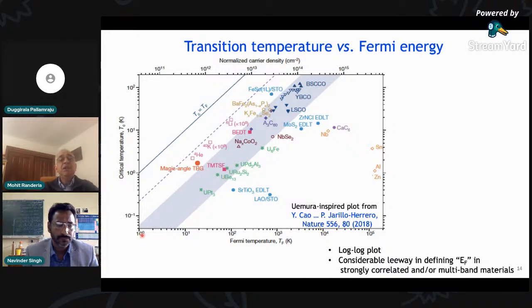But what they did in this plot is they took, I don't know, some more than 24 superconductors. And on the vertical axis, they plotted their transition temperatures and note a logarithmic scale. And on the horizontal axis, they plotted the Fermi temperature, or the Fermi energy divided by kB. Again, note the logarithmic scale. Now, of course, as any experimentalist will tell you, you can hide a lot of sins in a log-log plot. And secondly, you could also get into lots of discussions of how do you determine the Fermi temperature of some strongly correlated material or a multi-band system, whereas the TC is a measured quantity.